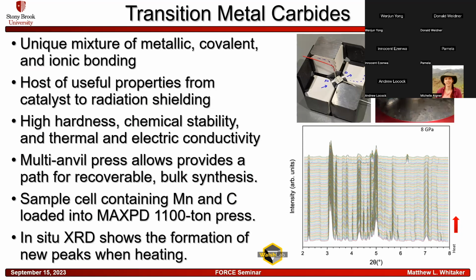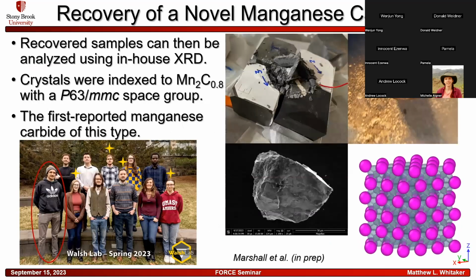So we had a sample cell in particular containing manganese and carbon, and we loaded it into the Max PD press. And the in situ X-ray diffraction, shown at the right, shows the formation of new peaks when heating the sample. Now, these recovered samples can then be analyzed using in-house XRD, and they did the structural refinement, and it was indexed to Mn2C0.8, which is highly non-stoichiometric, as it were, with a space group shown here. And this is the first reported manganese carbide of this type, and this work is part of Paul Marshall's thesis. He's the guy shown in the circle in the picture on the lower left. And currently we're iterating a version of this manuscript right now.